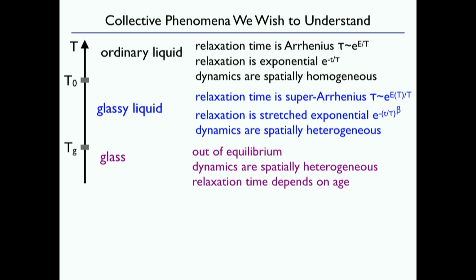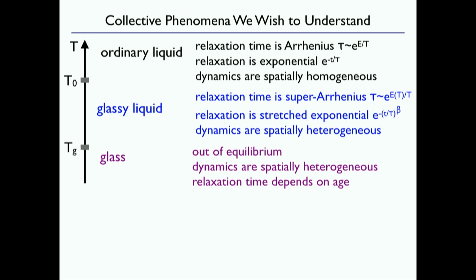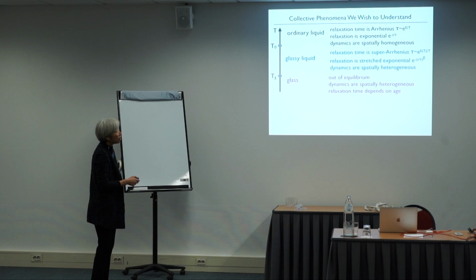And what is that? That if I look at the relaxation time, it's what's called Arrhenius. The relaxation time goes like e to some energy over T, right? And what is that? That is an energy barrier, or free energy barrier, right? So if there's a characteristic barrier size in this problem, then the Boltzmann constant tells me that the relaxation time, the probability of overcoming that barrier, should go like this, okay? And so the relaxation time increases as I lower the temperature. If I look at how the stress relaxes in time, it's exponential in time. And it's exponential with that time scale, with that stress relaxation time.